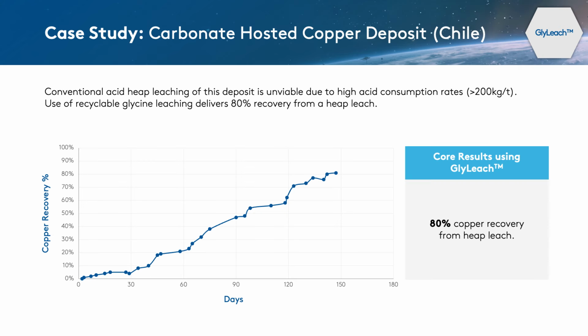Here's the first example of a carbonate-hosted copper deposit in Chile. For this specific sample, conventional acid heap leaching of this deposit was unviable because there was a huge amount of acid consumption, more than 200 kilograms per ton. So we used a recyclable glycine that delivers around 80% recovery from heap leach. As you can see in this graph, the y-axis shows copper extraction and the x-axis shows the days of leaching. So in around 150 days, we were able to extract 80% of the copper.